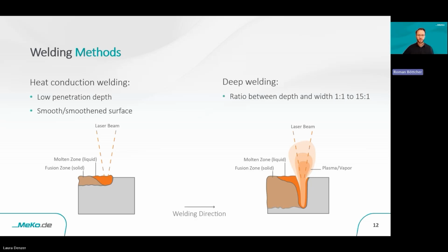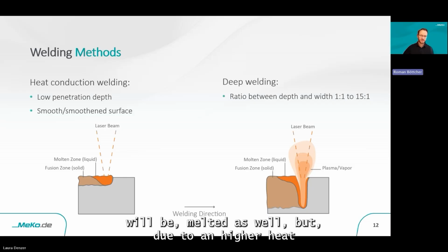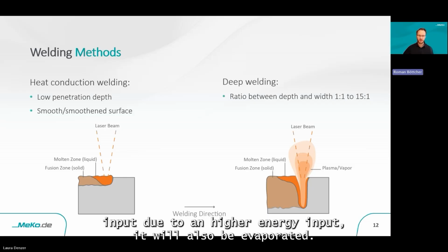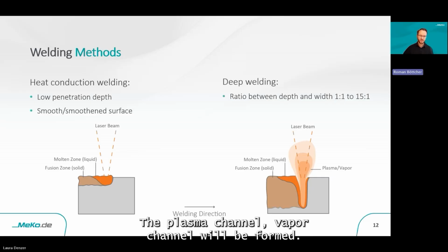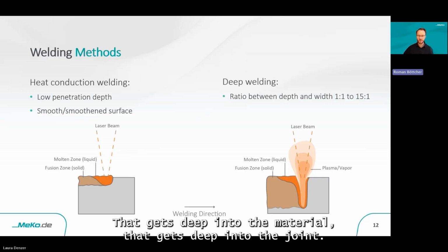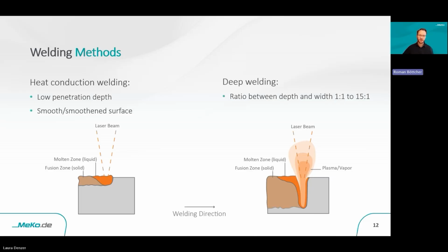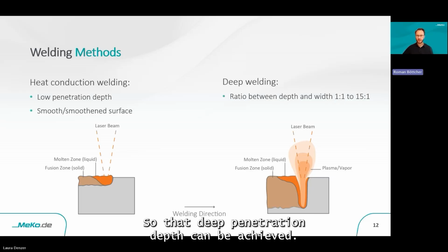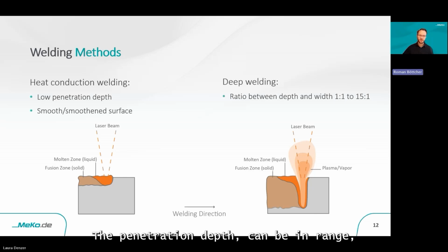welding techniques. On the right side, you can see deep welding. Here, the material will be melted as well, but due to a higher heat input, due to a higher energy input, it will also be evaporated. A plasma channel, a vapor channel will be formed that gets deep into the material, that gets deep into the joint, so that deep penetration depth can be achieved. The penetration depth can be in the range of 15 times larger than the welding width.